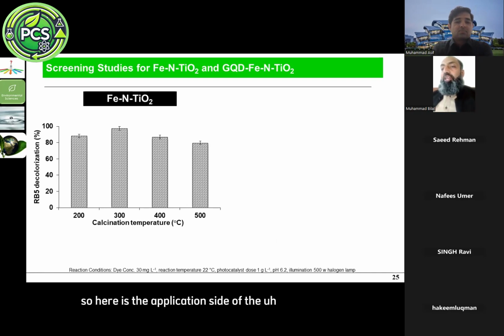So here is the application side of the different materials we prepared in our studies. First is the iron nitrogen titania, showing the RB5 (Reactive Black 5) decolorization at different calcination temperatures. And here we can observe more RB5 decolorization by this nanomaterial when it was calcined at 300 degrees centigrade.